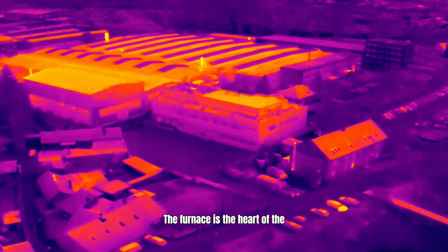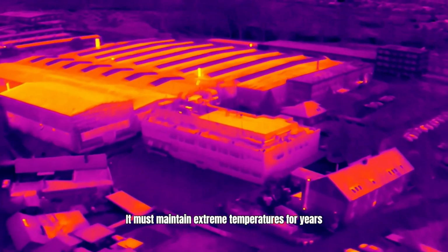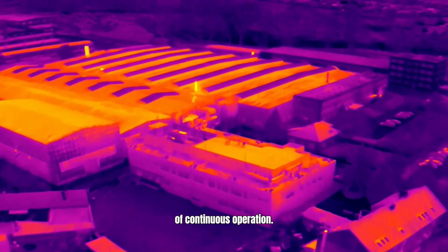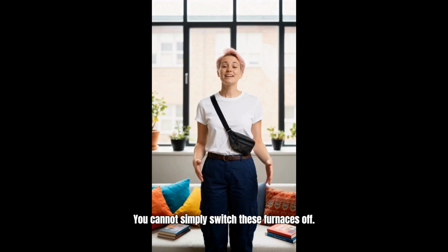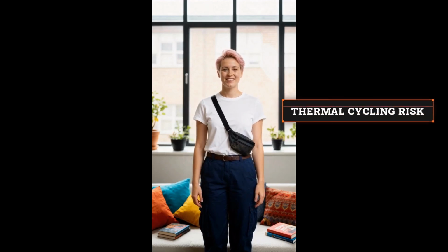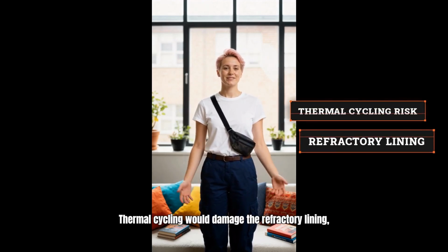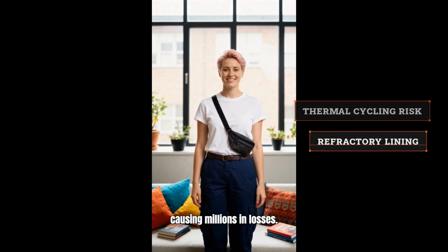The furnace is the heart of the plant. It must maintain extreme temperatures for years of continuous operation. You cannot simply switch these furnaces off. Thermal cycling would damage the refractory lining, causing millions in losses.